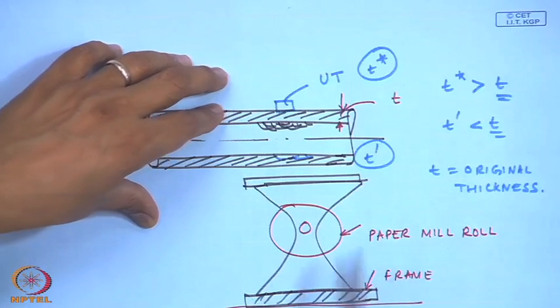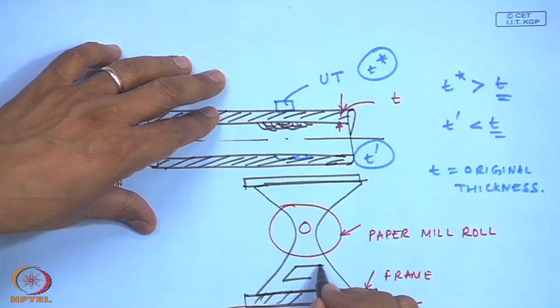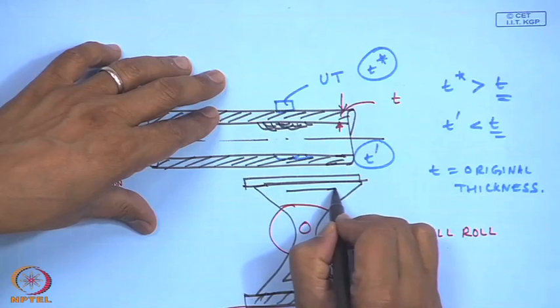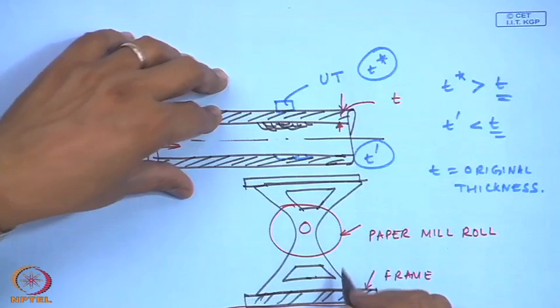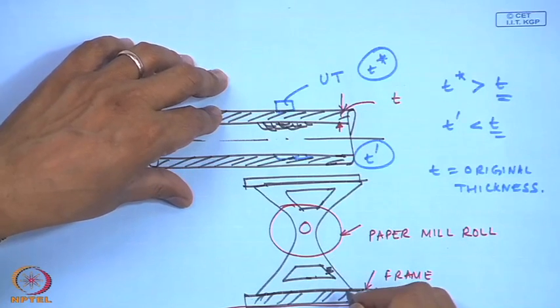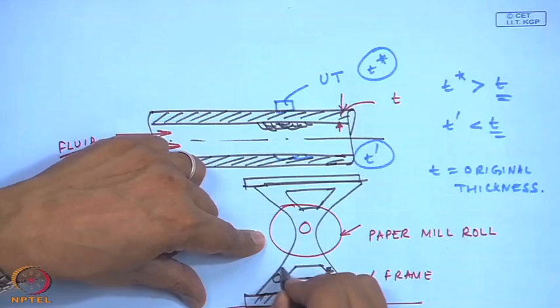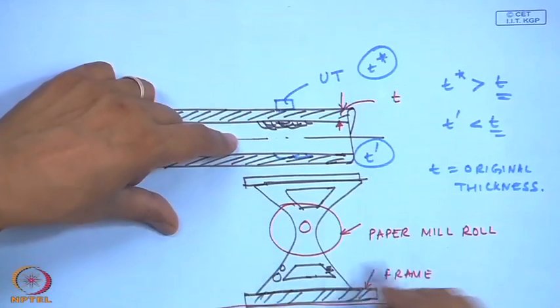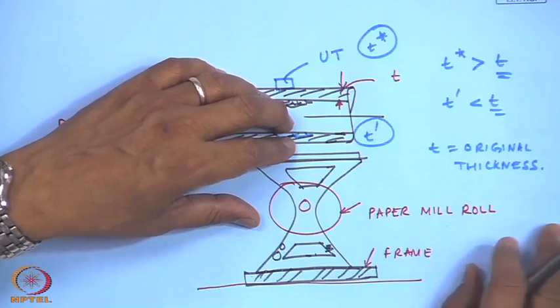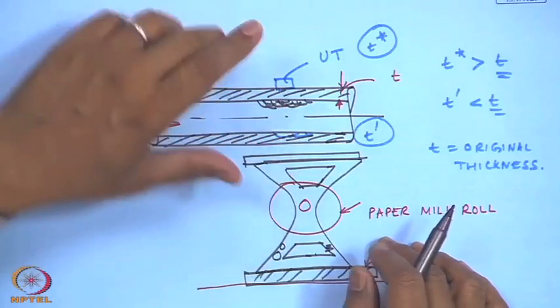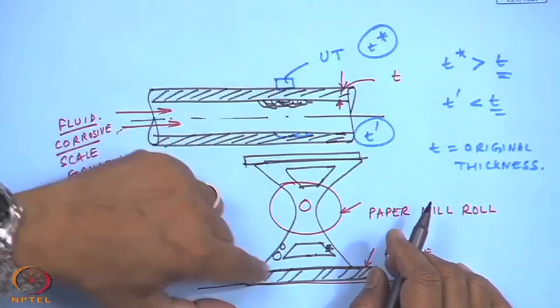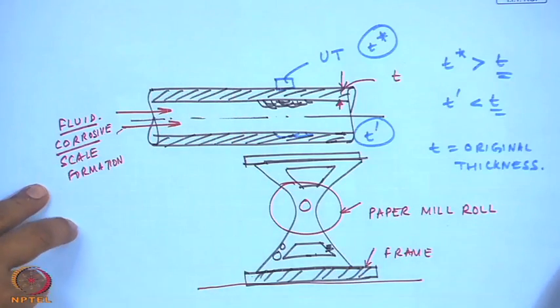So, in such a plant, there were cases where they knew this was steel, but nobody knew the thickness of this material. In such a scenario, we used to put ultrasonic probes and we were able to measure the thickness, and then we could reconstruct the entire plant machinery drawings, because once we knew the thickness, we could obtain the dimensions. So, what I mean to say is, a lot of unknown thicknesses can be measured using ultrasonic probes, because you have access from the outside, and then you can know the thicknesses at the appropriate places. This is one area where ultrasonic is used.